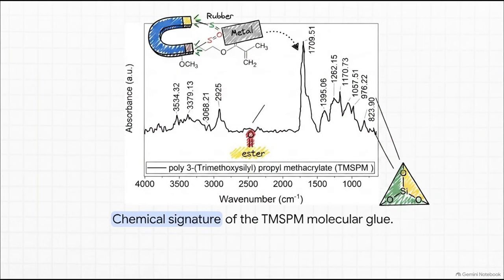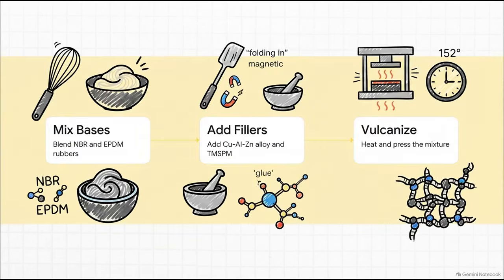If we look at the ATR-FTIR spectrum, which is basically a chemical fingerprint, we can actually verify this molecular glue at work. You've got these very specific peaks on the graph, like the ester stretch at 1709, or the silicon-oxygen vibrations around 1057. And they verify its unique chemical structure. This is the exact signature of the vital interfacial adhesion that allows the rubber and the metal to become one unified composite.